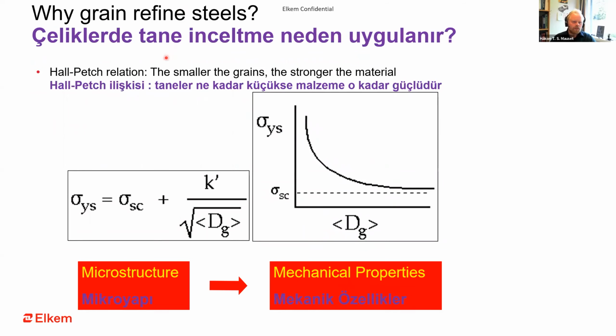Well, when we grain refine steels, then we can, for example, look at the mechanical properties and the Hall-Petch relation. This is the Hall-Petch relation, and it clearly shows us that the smaller the grains, the stronger the material. So when we see this from the curve here, the smaller the grain size, the higher the yield strength. So we actually see that by playing with the microstructure, the grain size, we get better mechanical properties. And also the nice thing about grain refining is that you don't only get strength, you also get better toughness during grain refining.